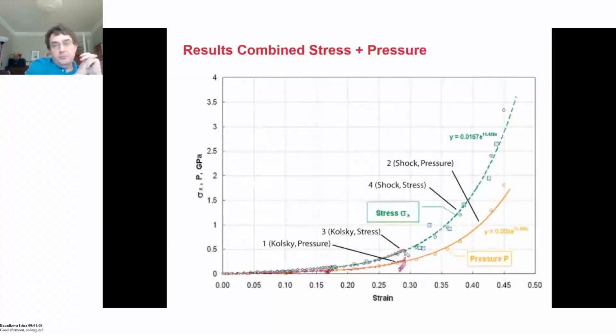If you take the shock pressure and combine it with the results from the quasi-static bar or the Hopkinson Pressure Bar, what we have here is the results from the Hopkinson Pressure Bar down here, and you have the response of the shock experiments at these points. So we were able to have a good overlap in stress in the system. And we compared that to the strain in the system. And again, you could do the pressure calculations if you assumed that the Poisson's ratio, or the lateral thrust of the system, was maintained in the same relationship as was seen in the Hopkinson bar.